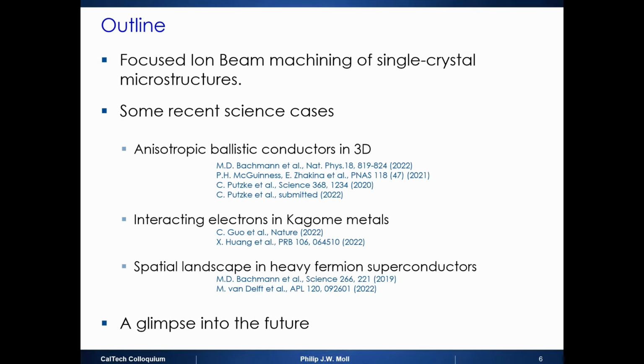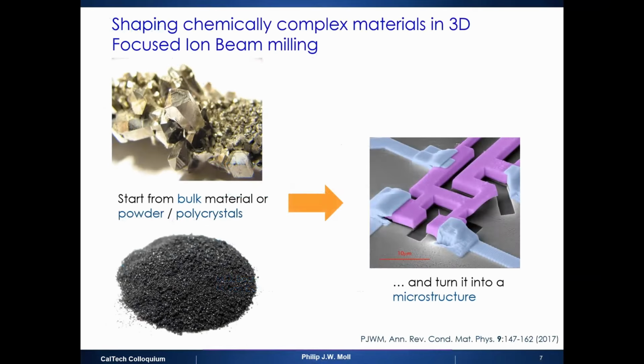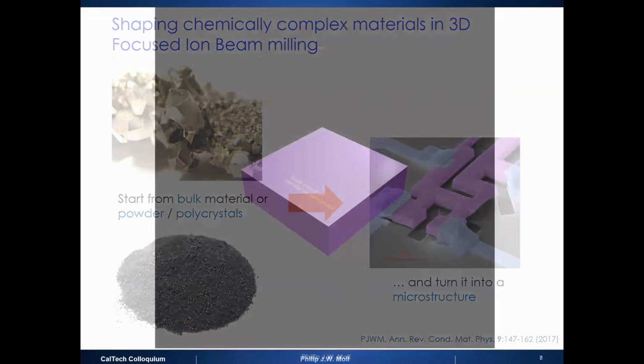Okay, let me start with focused ion beam machining. So the challenge now is that you can't just go on universitywafers.com and buy your cuprate in a 15-inch wafer and then process it. It comes as single crystals. It comes as maybe polycrystalline blobs with strange phases, maybe it's only powders. Some of you have very strange starting materials. So a lot of the traditional lithography methods are out of the window anyways because of the shape and the form of these materials. But you want to use this to start with to then get to structures that are in the, say, submicron to many tens of micron size to then study them in hybrid chips. And that's what we're doing with our focused ion beams.